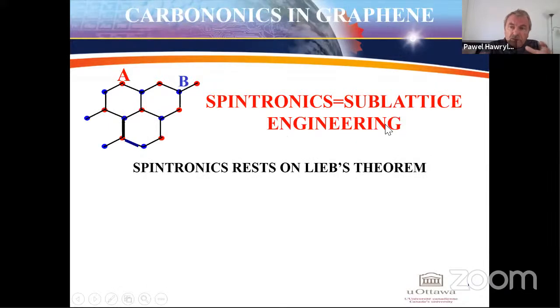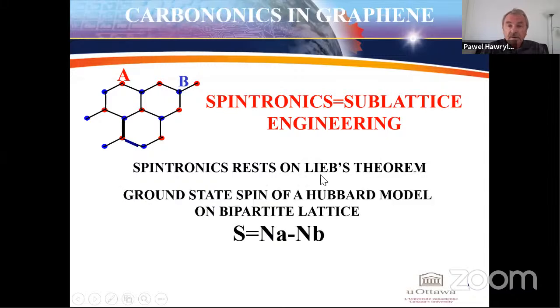So this was when we examine the triangular structure, it turns out that it consists of two unbalanced sublattices, and the difference between these number of atoms in the two sublattices is responsible for build-up of the magnetic moment. So the spintronics, the magnetism of these structures rests on Lieb's theorem, and Lieb's theorem states that a Hubbard model on bipartite lattice has a ground state spin proportional to the difference of these red and blue atoms.